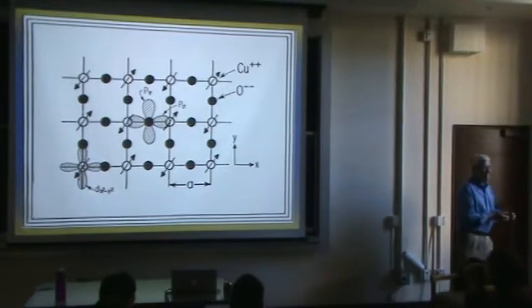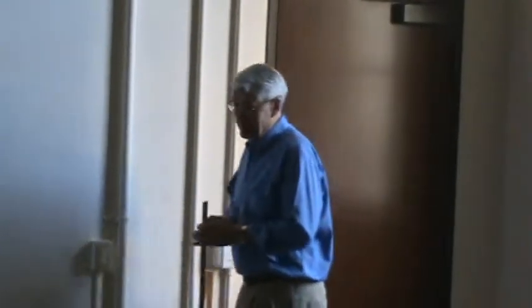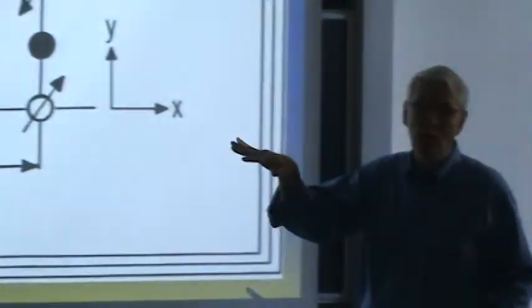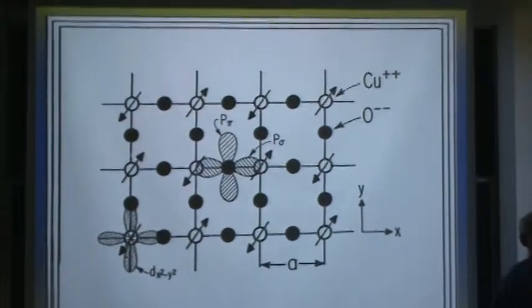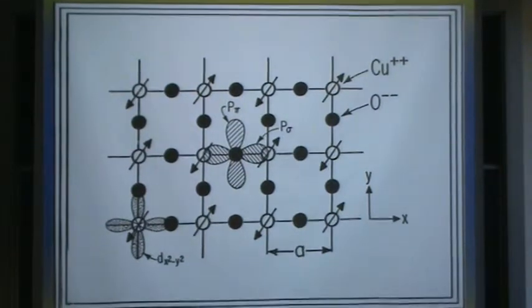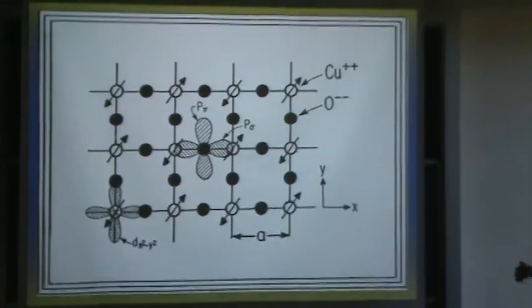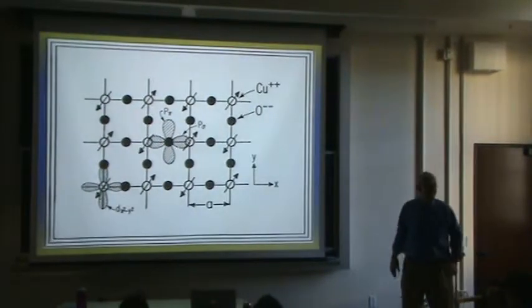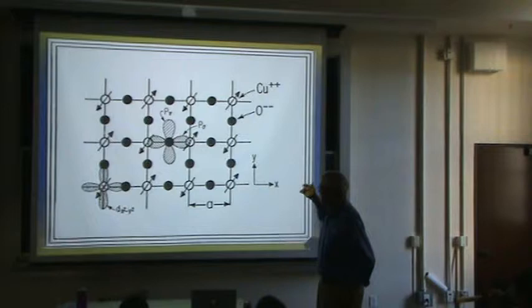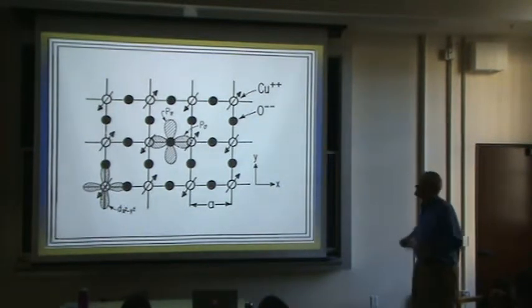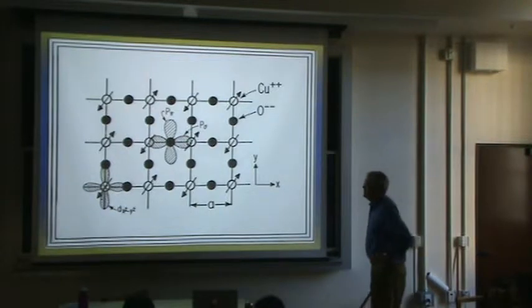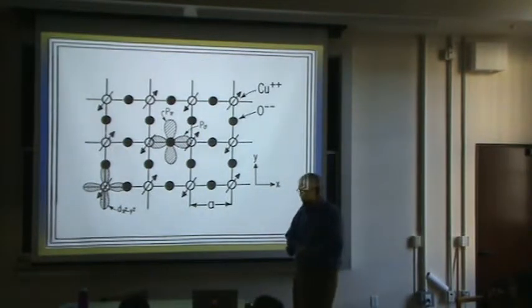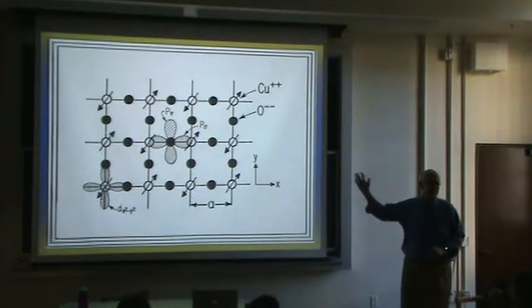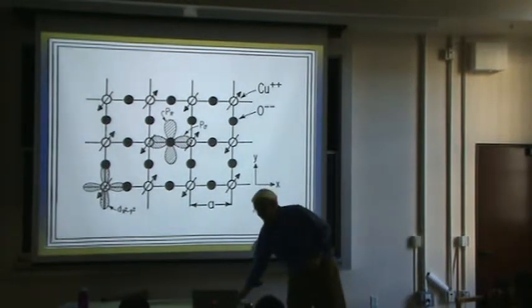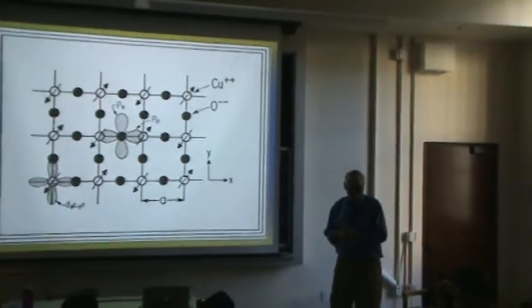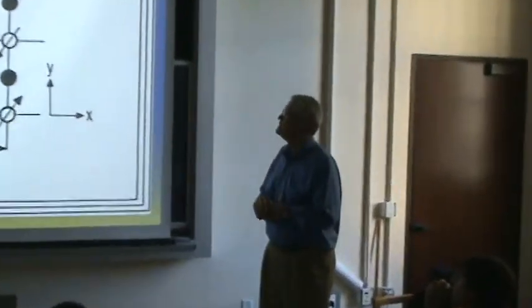So the really nice thing about having discovered that these materials, every single one of them, no matter what's in the sandwich, are composed of a copper oxide layer, is that you can convince yourself that all you really need to do is solve the problem of a single layer of copper and oxide. And so we can isolate our interest and attention onto that. Since I have only a couple minutes left, it would take much too long to explain where this comes from. But let me give you the essence, and then I'm going to jump to the newest materials.